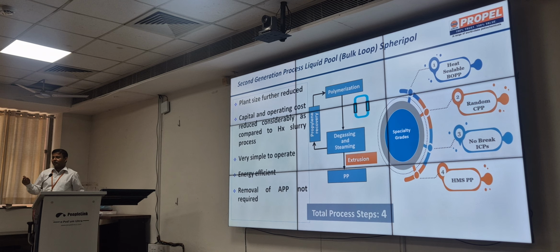For BOPP, all the confectionery products, the chips, the inner layer is BOPP, heat sealable BOPP is used, and this heat sealable layer thickness is only 1 micron or 2 microns. And most of these grades are imported right now. No domestic manufacturers are producing such kinds of grades. Random copolymer grades you can produce. ICP impact copolymer grades, better ones you can produce. High melt strength polypropylene.